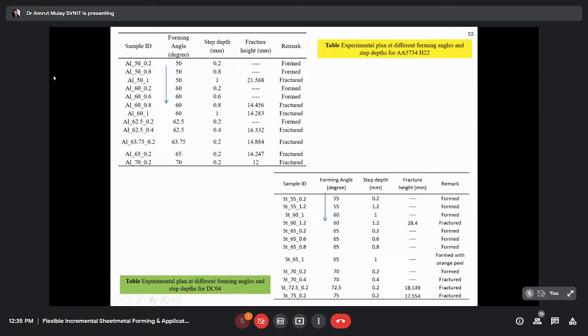Now we can see 60, 0.2, 60, 0. Now here you can see when you go to angle 60 with 0.8 mm, now the limiting 0.8 mm, when we take the step depth, the fracture is taking place at a fracture height of 14.456. It means that the formability is further reduced.